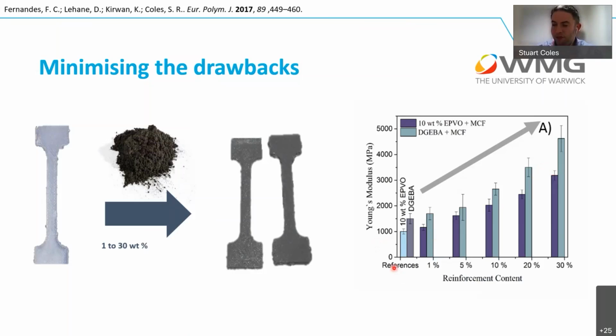The DGEBA system is always better in terms of its Young's modulus in comparison to the vegetable oil one, but you can see a steady rise, and we're getting well over where we started. So if we wanted to get back to that product system, or at least match or exceed it, then the use of the milled carbon fiber was a simple way of returning those properties and getting them back up. And we can see here that we've got 30% milled carbon fiber with the 10 weight percent of the epoxidized vegetable oil.